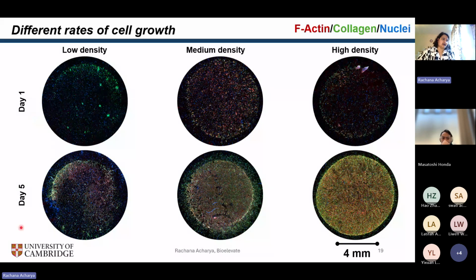Sure enough, if you observe them on day 5, you can see that the low density cells have grown, but not in all parts of the scaffold. For the medium and high density, the cells are growing in the entire scaffold, almost covering it completely. The color mapping is blue for the nuclei and red for the actin, or the skeleton of the cell. We also notice that collagen, a very popular ECM protein, is secreted in large amounts as the cells grow within the scaffold. So we have three conditions with three different densities of fibroblast cells, which are clearly growing at three different rates. We want to see if we can measure this electrically as well.